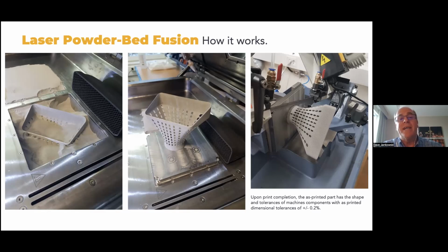This is the inside of the build chamber. In the left-hand photograph, you can see a part in the build cylinder, with some powder surrounding it. What will be conducted next is you would use a vacuum in order to remove the excess powder, which can then be repurposed and reused. That's another advantage of this laser powder bed technology: you don't have a lot of waste. Any powder you do not use for a specific part, you can remove, re-sieve, and then replenish the feed cylinder in order to repurpose the powder.